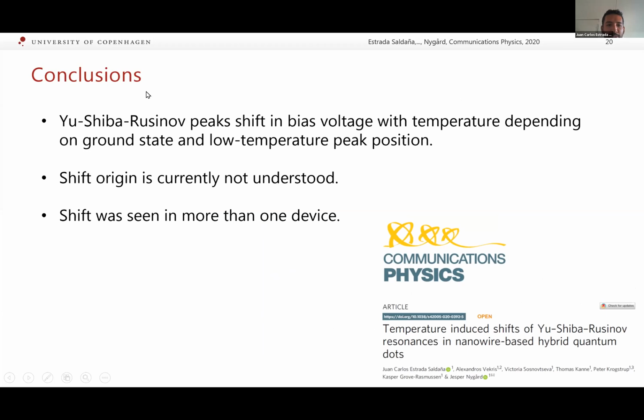I have shown you that experimentally, at least in one device, usually the peaks shift in bias voltage with temperature, depending on the ground state and their low temperature peak position. And well, the shift is currently not understood. And well, the shift has been seen actually in more than one device. We show data for another device in our publication, which you are invited to consult.